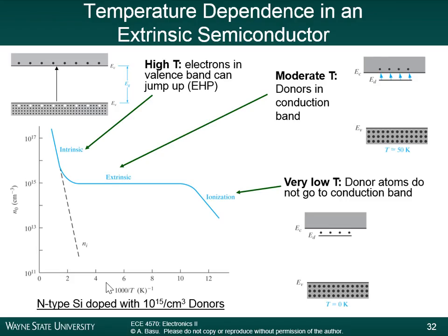For high temperature applications, you actually need large band gap semiconductors so that this effect doesn't happen. This is one of the reasons why diamond was being investigated as a potential semiconductor material for very high temperature applications. So if you're working inside an automotive engine, another material that was being investigated was something called silicon carbide, where you have a combination of silicon and carbon atoms. They're both column 4 elements, right? So they form those tetrahedral bonds. But silicon carbide also has a larger band gap than silicon does. So those are useful for higher temperature applications where you want to prevent the semiconductor from going into the intrinsic zone. All right. We generally operate our semiconductors in this region here.